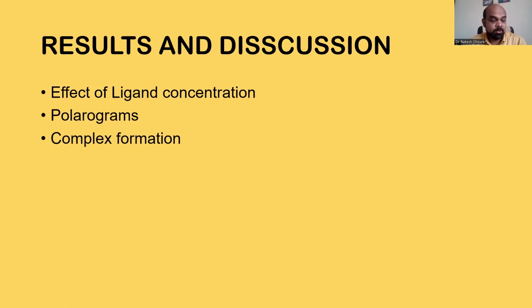Effect of ligand concentration. On increasing the ligand concentration in each set and subjecting these experimental sets to polarography, it was observed that the half-wave potential shifted to more electronegative value. The plot of change in half-wave potential with logarithm of change in ligand concentration yielded a straight line, suggesting the formation of a single complex species in case of copper atropine system. With the help of Lingane's method, the polarographic data has been obtained. Some IR spectral analysis and pharmacological experiments were also performed in this section.